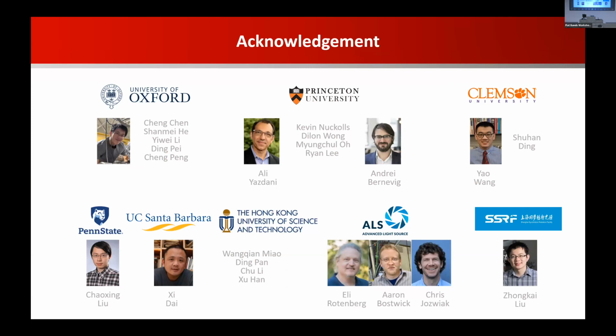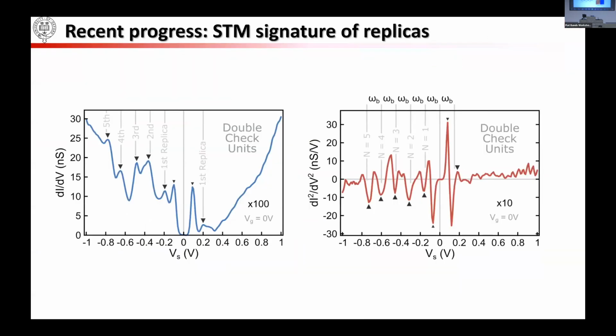Because we cannot put on the top gate, you can ask why we don't use the back gate. Yes, we tried. If the hBN is too thick, you cannot gate it effectively. If it's too thin, the hBN quality is not so good, and with the X-ray shining on the sample it causes a leak, so we cannot gate it very effectively. So in the end, we found this thermal population was the way we went. But more recently we have been trying to gate it. We continue our effort and got some results, and it's quite interesting. Let me show it here.